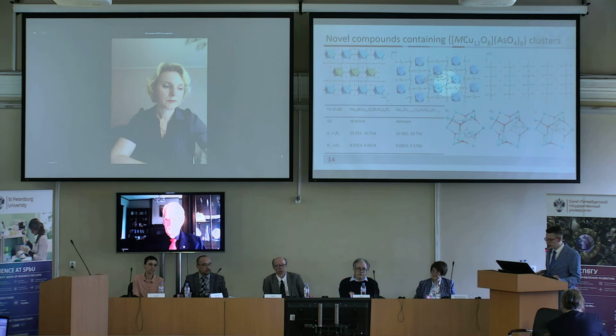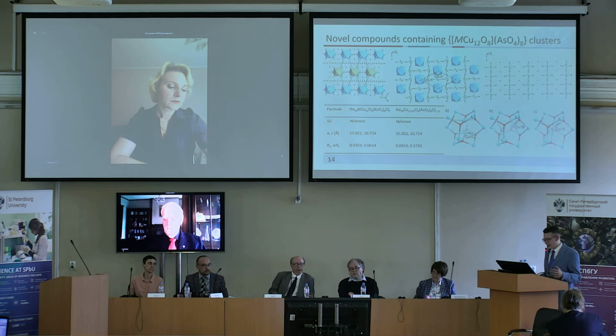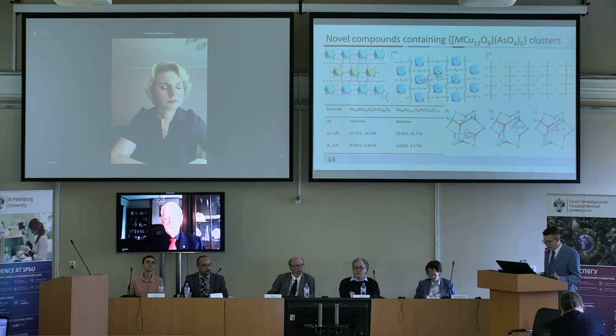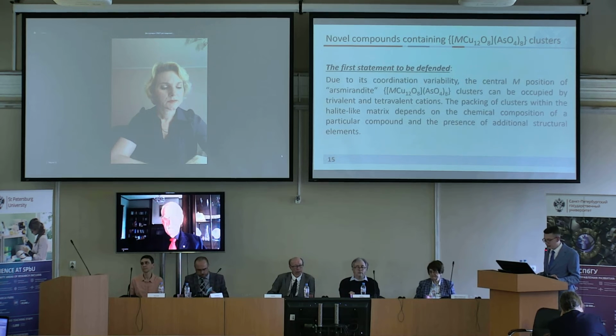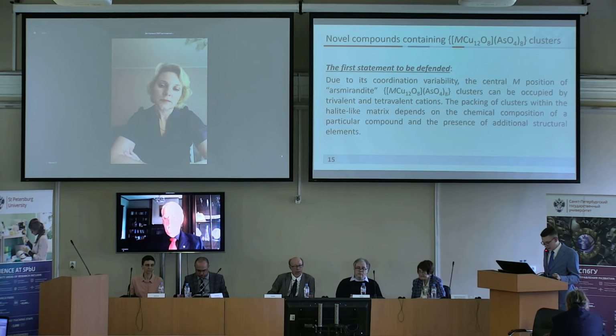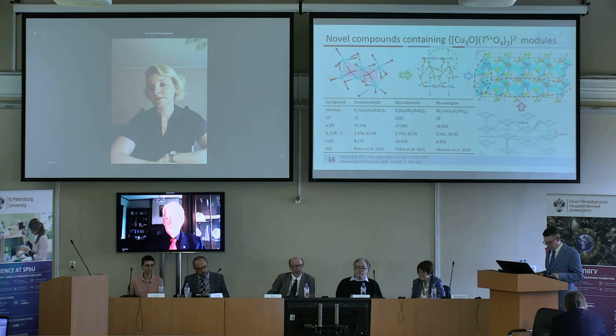In addition, as the experiment demonstrated, crystallization of the purely copper-containing phase is also possible. With the copper atoms located in the center, 3 ordering schemes are possible, shown in this slide. Thus, the demonstrated data indicate both the flexibility of the clusters themselves and their halide-like matrix. Indeed, the bonds between oxygen atoms and the central cation vary from 2.1 to 2.4 angstroms, and the halide-like matrix is able to adapt both to different packing arrangements and different degrees of distortion, which takes us to the first proposition submitted for defense. Due to its coordination variation, the central M position can be populated with either trivalent or quadrivalent cations. The packing of clusters can vary depending on the chemical composition of the compound.